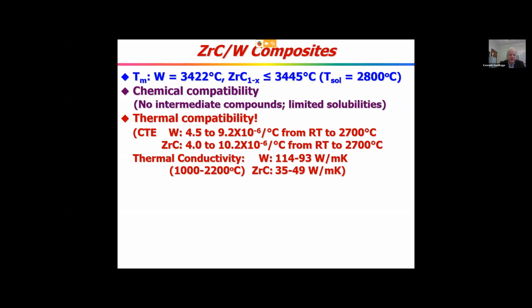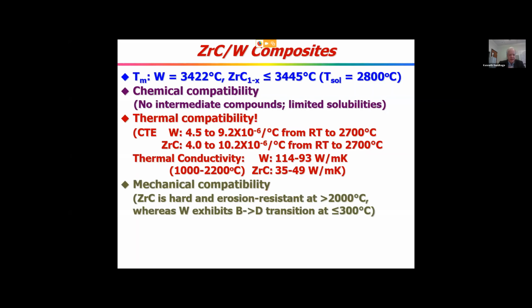What's more, both phases, tungsten and ZrC, are quite thermally conductive, which is important for heat exchanger applications or for just removing heat from a hot base. They're mechanically compatible. That is to say, the carbide provides the hardness and erosion resistance that you need for this application at high temperatures. Tungsten becomes ductile at or about 300 C, and so the composite is tougher than zirconium carbide by itself, and certainly more erosion resistant than tungsten by itself.